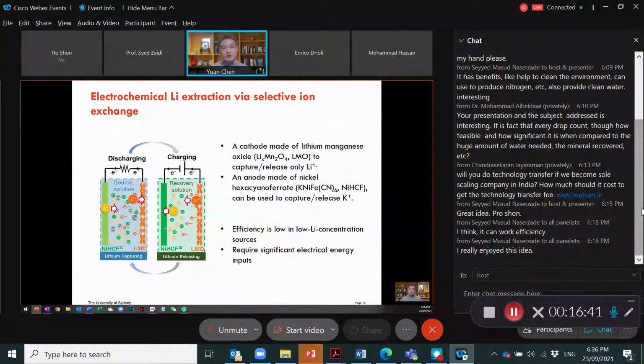So during the discharging, we insert the lithium into the LMO and release the potassium into the solution to have a charge balance. While during the charging, we do the reverse steps. The advantage first is of course that it is highly selective, and also much faster than other lithium extraction methods from brine. But the problem is they are not very efficient if the concentration of the lithium source is very low. In some situations, for example, if you want to extract lithium from seawater, the process is so slow that the lithium will not be able to go into the electrode.